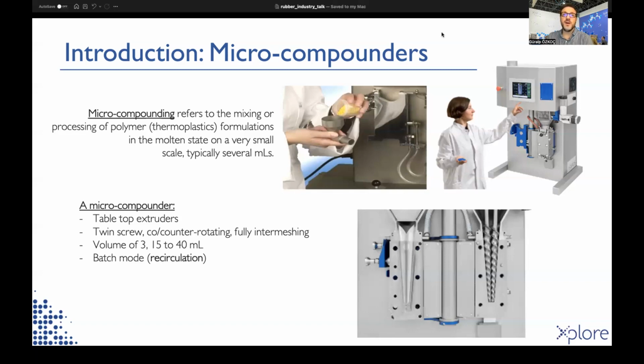The robust design ensures the generation of reproducible and stable data for years, and the vertical position of the liquid-tight barrel allows the processing of low viscous fluids down to 10 Pascal seconds. The screw speed can be set between 1 RPM to 500 RPM, and the barrel temperature can go up to 500 °C. We have 40 Newton meters of torque over 15 milliliters of material volume.